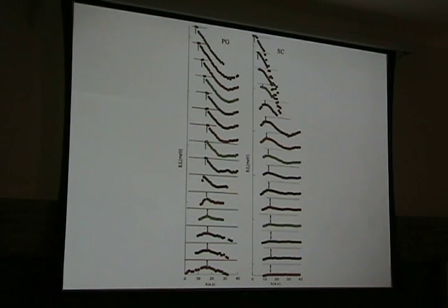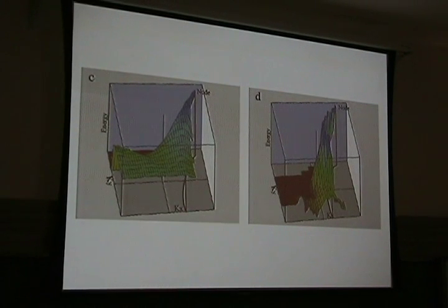Okay, so let me show you in a different view. This is a three-dimensional representation of the dispersion: energy, momentum, in two directions. So here, superconducting state. You can see that the gap opens right away, and you can always see this backbending from particle-hole mixing. Now in the pseudogap, I'm sorry the data is not as good, but at the node the data is just going straight up, okay? Dispersing as fast as here, and then all of a sudden the pseudogap appears here, okay? And whenever the pseudogap appears, even though it's not necessarily in the straight part of the Fermi surface, you see this backbending. And this momentum is always a Fermi momentum. So we think it's not due to some charge order, it's something else, okay? It's tied to the Fermi surface, always.